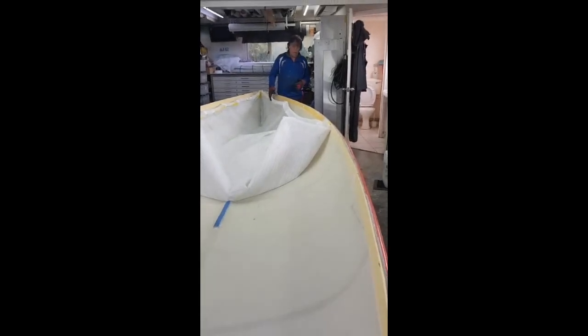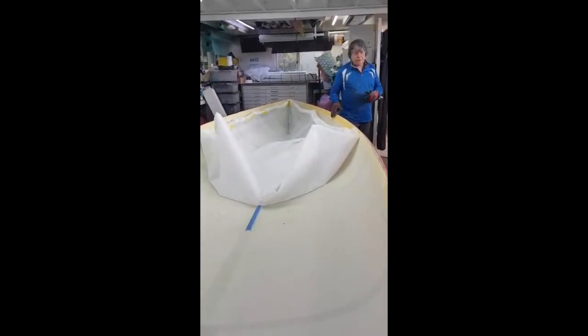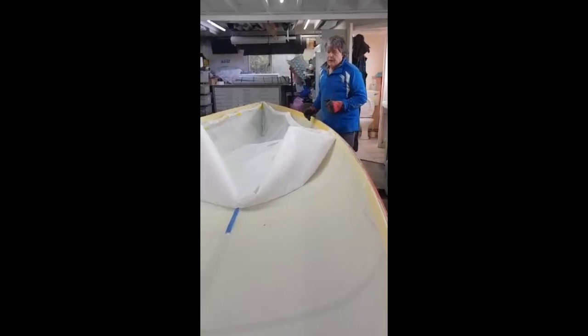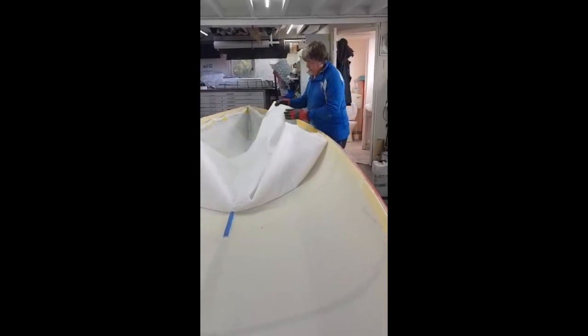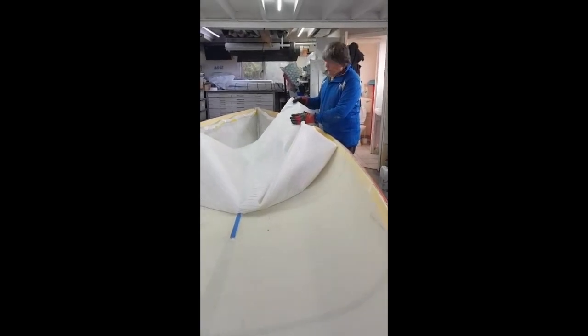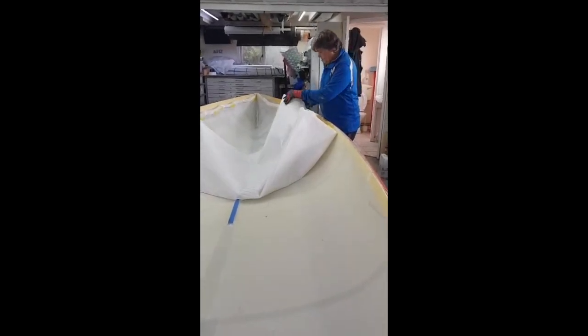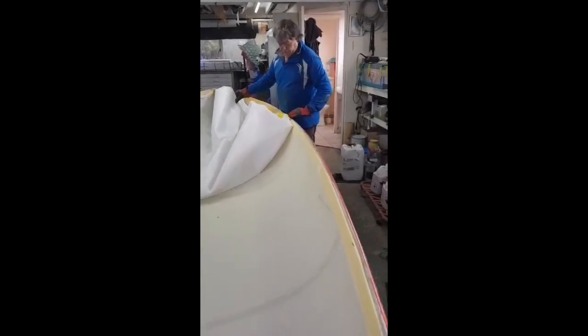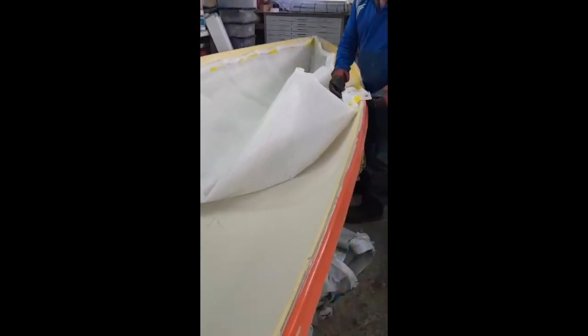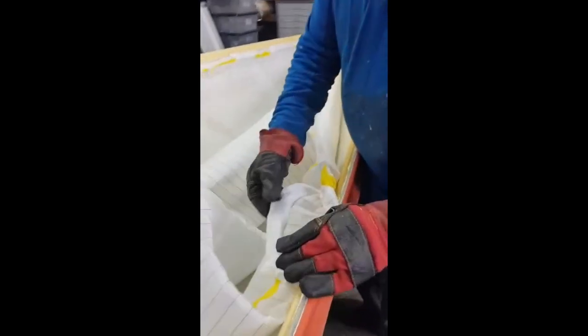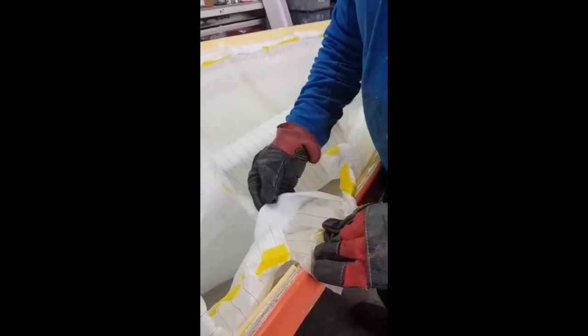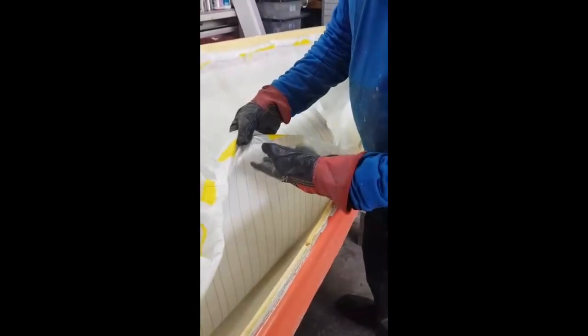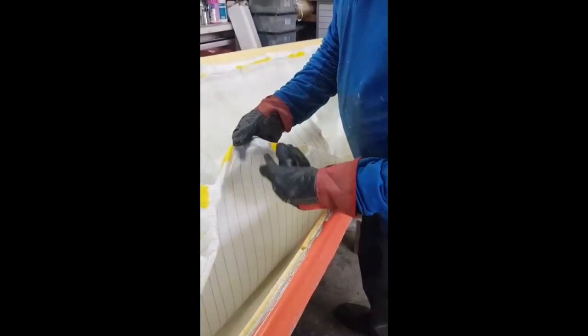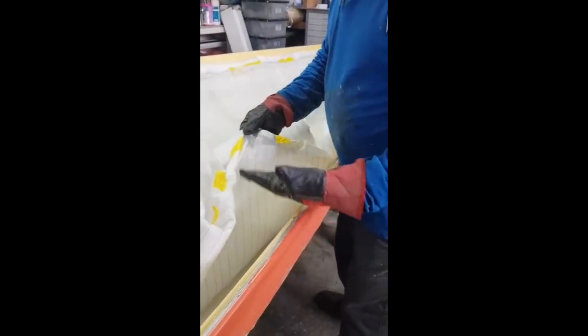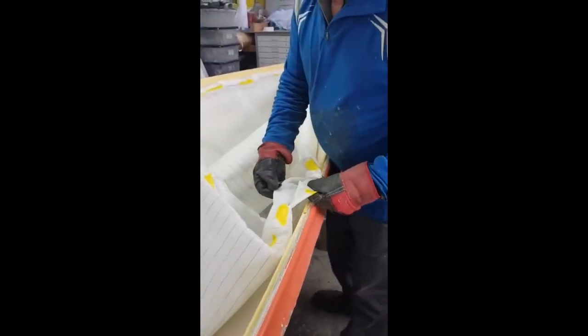We've now removed all the insulation. We've removed the vacuum bag, and we're now removing the peel ply, which is this stripy material. This includes the breather cloth, which is on top of it, which is this white cloth here. Now that white cloth has absorbed any excess resin that was in the laminate, and it passes one way through the peel ply because it's been driven down by the vacuum, so it comes out of the laminate and gets absorbed into the breather film.